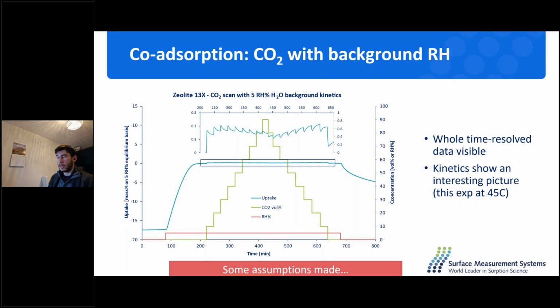There are some assumptions made. In the previous isotherm that I showed, the assumption was that when CO2 is added, it does not displace any water. And if we zoom in a little bit on the kinetics, that does not seem to be the case.